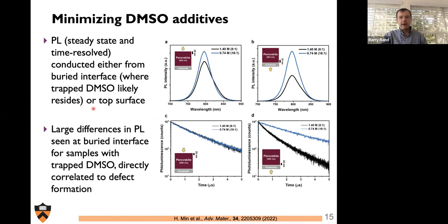The time resolved photoluminescence shown in the bottom shows negligible difference when excited from the top, but from the bottom we can see that the one with the DMSO trapped in there has a considerably shorter lifetime compared to the one without that considerable amount of DMSO trapped there. And so I think with these data, we can pretty confidently say that the presence of DMSO is not a good thing.